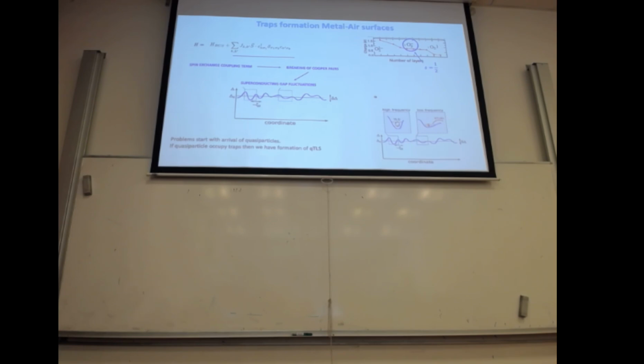So this somehow closes what kind of spins you have at the metal-air interface and how they can relate to the noise. Now I told you that there is another feature: if you have a spin 1/2 that is close to the superconductor, then you have this sort of interaction, and you might break a Cooper pair. And what we think is that because of this, of course there may be other mechanisms, one expects that there are superconducting gap fluctuations. And the typical scale of these superconducting gap fluctuations is of the order of the gap.